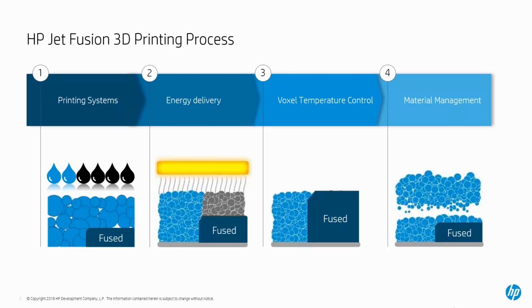The technology works with print heads. So we stagger 3 different print heads across a print bar, and then we essentially do 2D printing, right? We disperse the agents just like you would on a piece of paper, and in those locations at the same time where the droplets are dispersed, we have infrared energy that follows that, which applies it to the powder, and it's absorbed into the agents, mainly the fusing agent, which is actually black. If you think of it as like a black car outside on a hot day, it absorbs a lot of heat. So the energy is going to be attracted more into the areas where the fusing agent is, which brings it above the melting point, and then the part melts, and then the bed lowers, and then that process repeats itself over and over and over again.